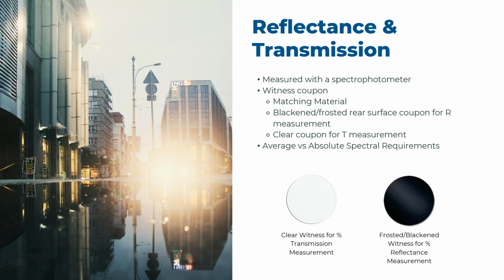The spectral requirements, when they're written on a drawing, are typically specified as an average requirement or an absolute requirement. Now, overall, that doesn't seem like a huge difference, but it definitely is. Average requirements basically state that over the specified wavelength range, the permitted amount of reflection or transmission will meet an average number that's agreed upon. Now, an absolute specification, just as it sounds, means at every point throughout the operating band, the absolute requirement must be met. Doesn't seem like a huge difference, but it is.